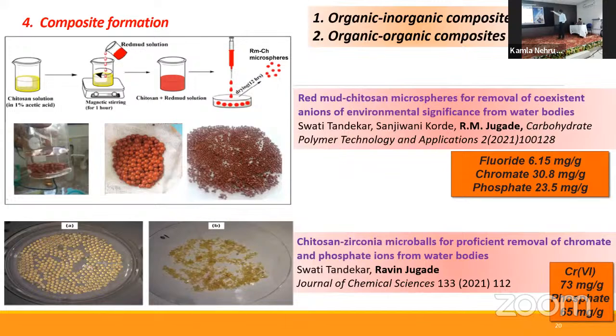You will find that it can remove fluoride, it can remove chromate, it can remove phosphate simultaneously, all of them. Another example is chitosan with zirconia microball. It is formed and the composite was found to have very good phosphate as well as chromium absorption capacity.